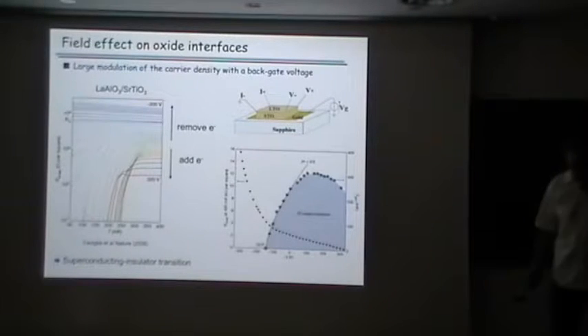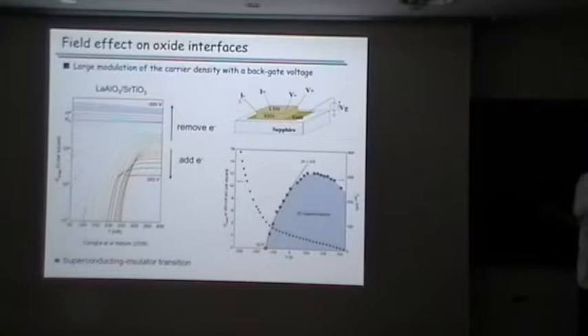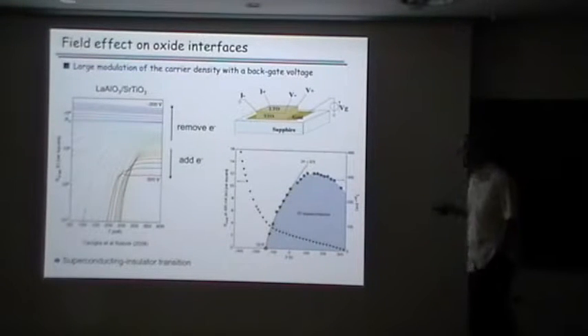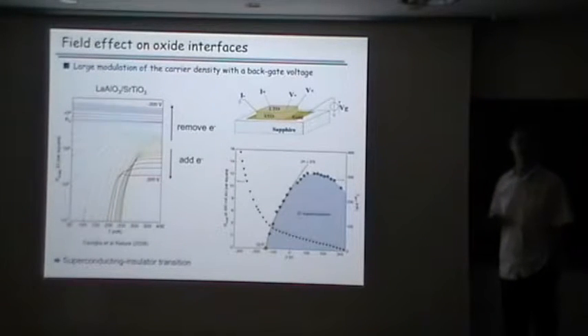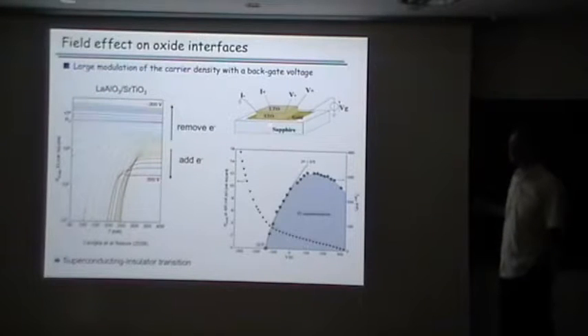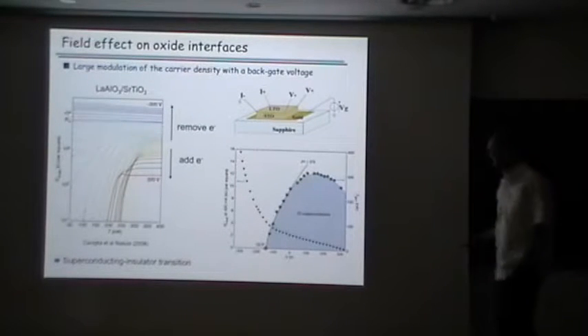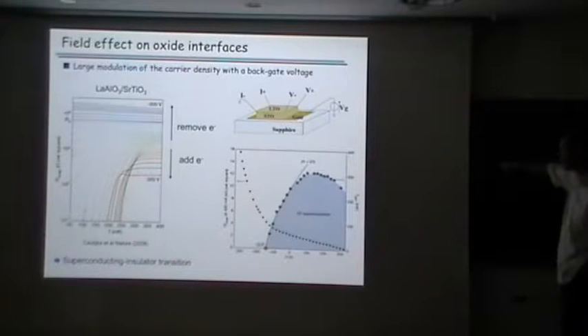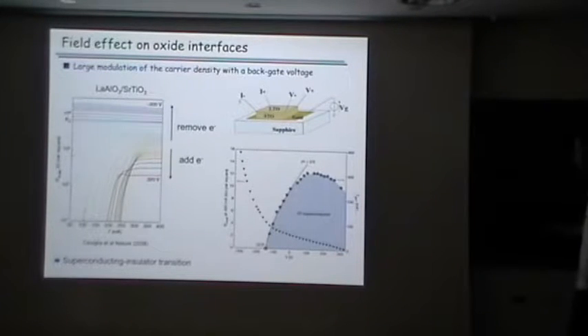Okay, so the nice thing about this system is that since it has a rather low carrier density, you can put a gate, for instance a back gate on the substrate, and modulate the number of carriers. And of course that's very interesting for the physics. It's essential for the technology. You can use them to make a transistor, for instance. And what you see here was found in 2008 by the Geneva group: you can remove electrons and get a transition from a superconductor to an insulator. And if you add electrons, then the superconducting transition goes up and then down again.